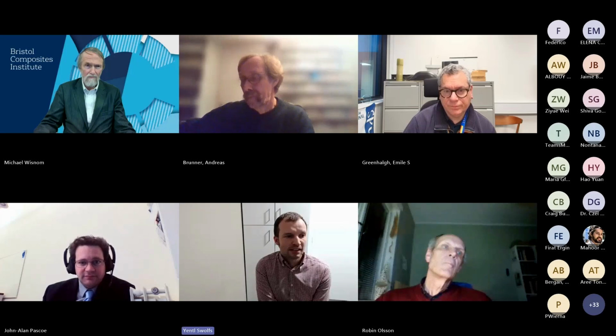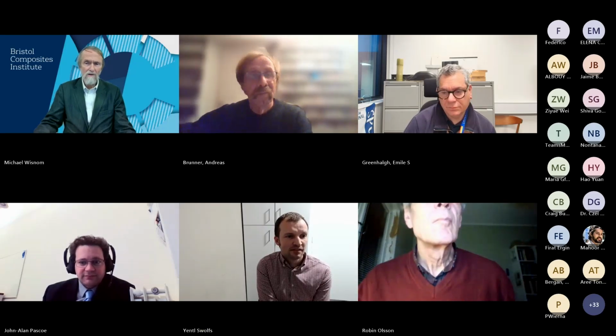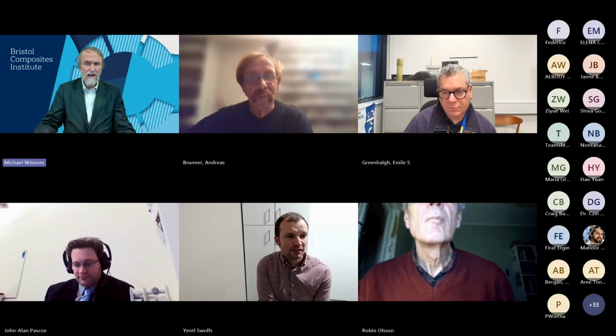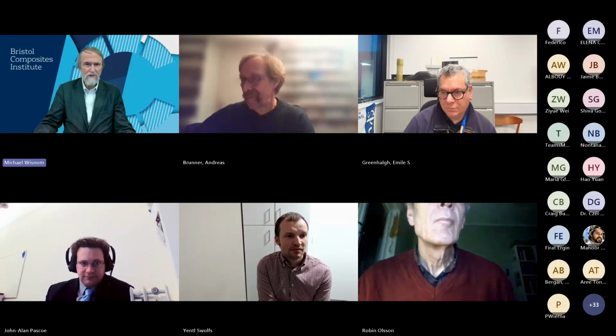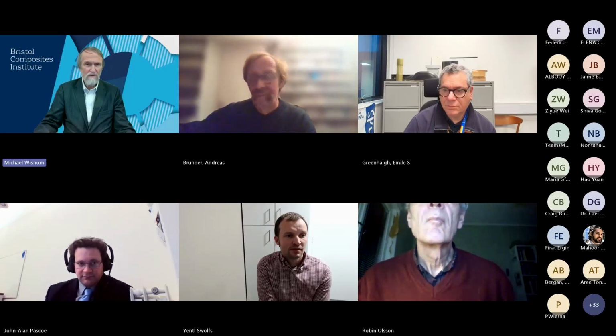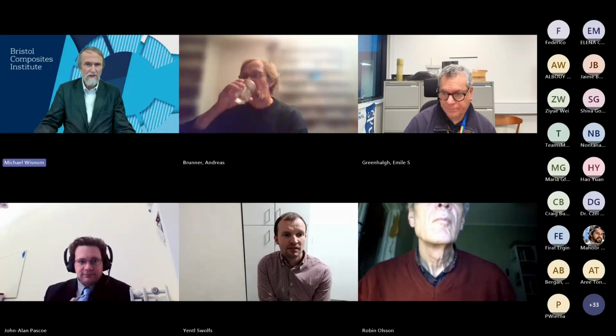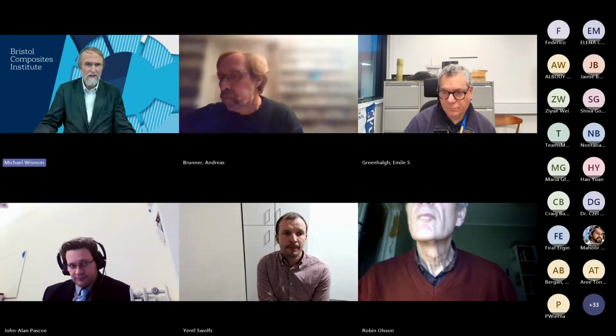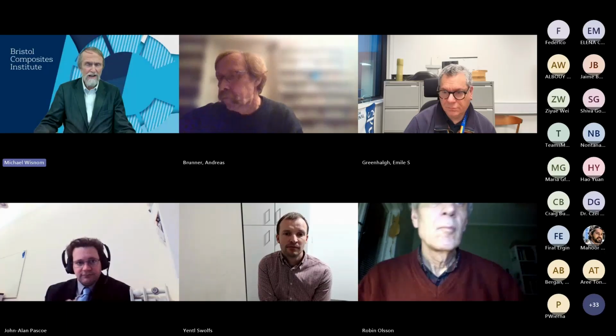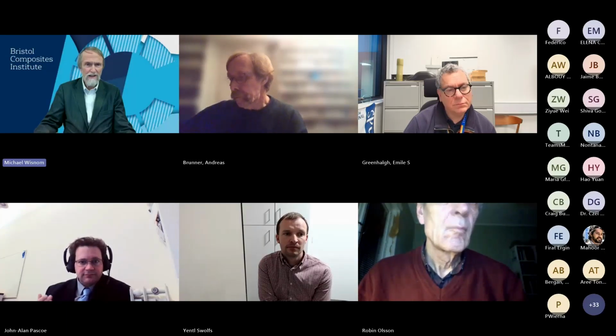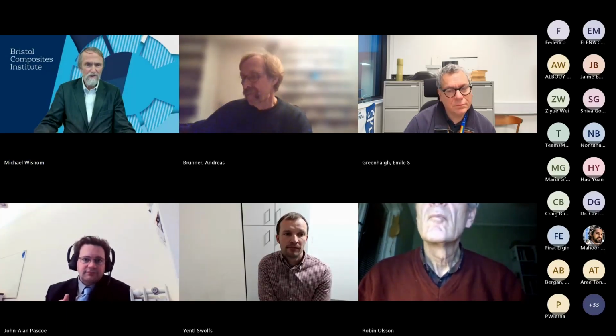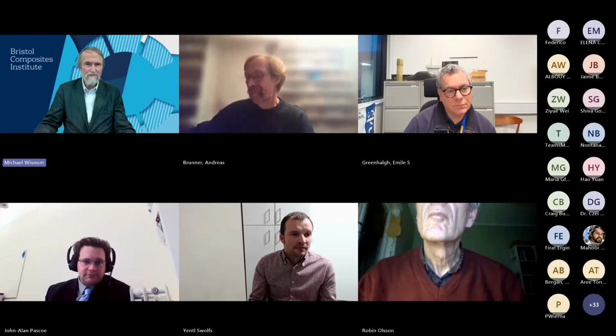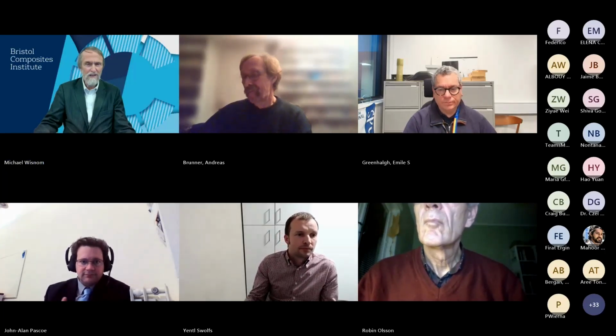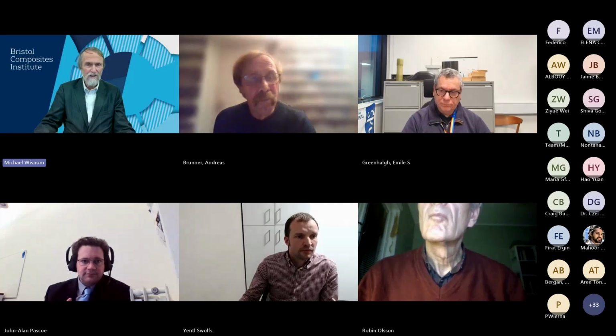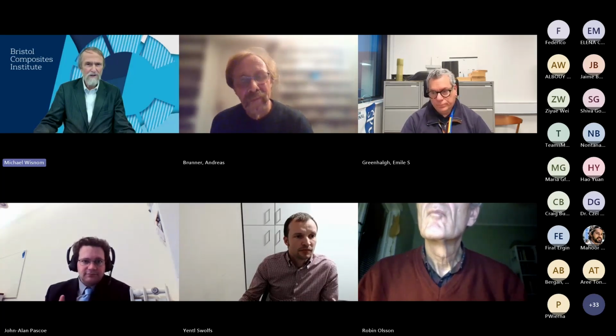I agree. Anybody else want to comment on that one? Well, just a clarification about what we're talking about with VCCT. Are we talking about what's in Abaqus, for example, where you use the Abaqus interface approach? Because you can, in principle, use a virtual crack closure even if the crack is not self-similar. You just work out the energy balance from propagating a crack versus not propagating a crack. And that's not how it works in Abaqus, but in principle, I think you can calculate it.